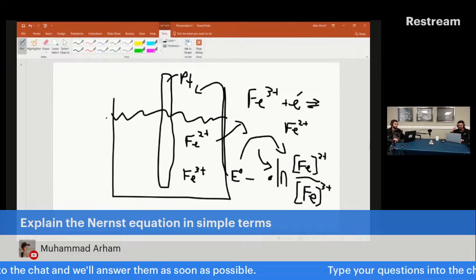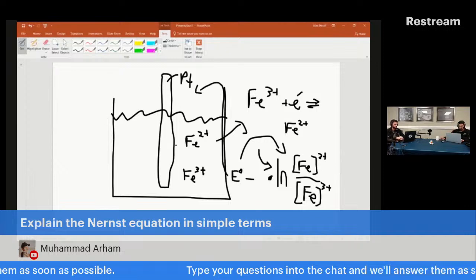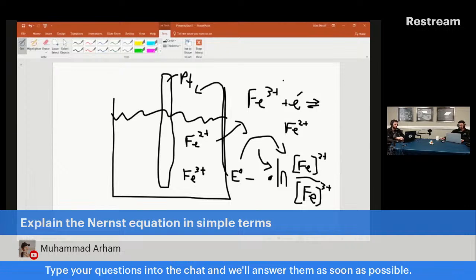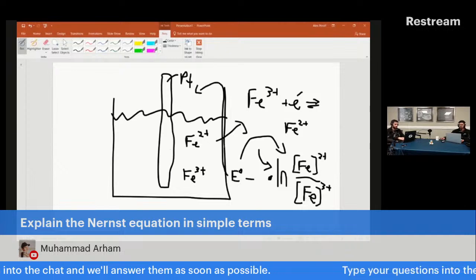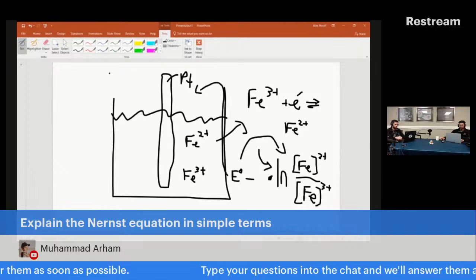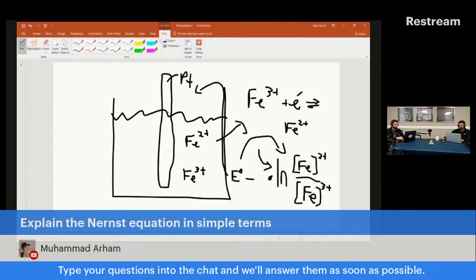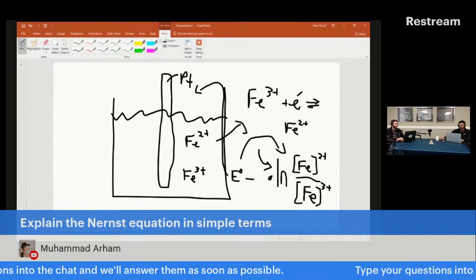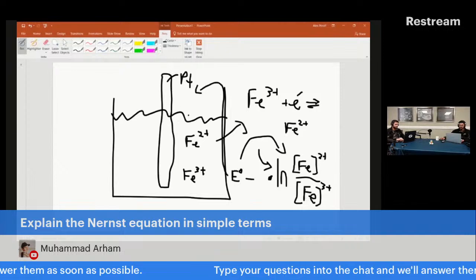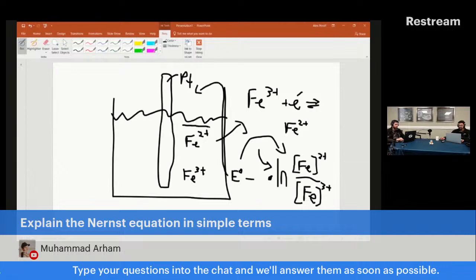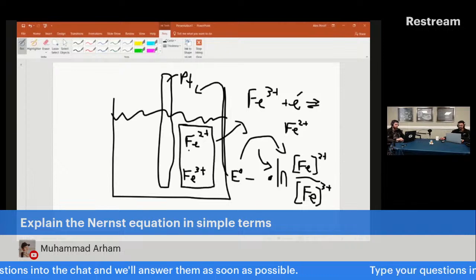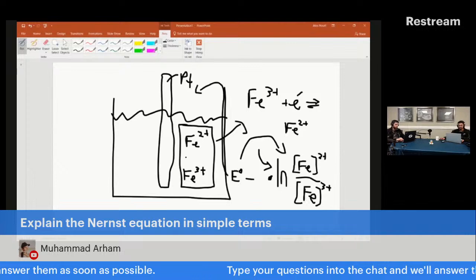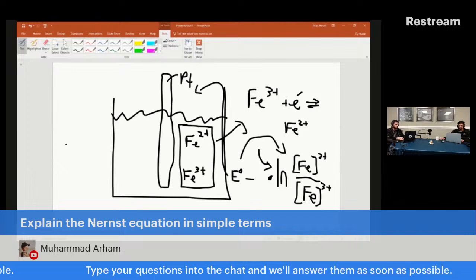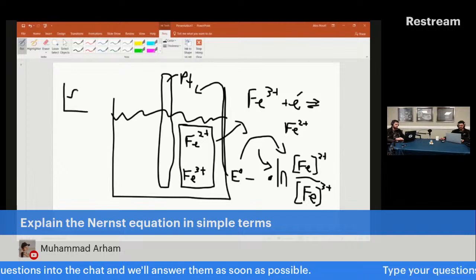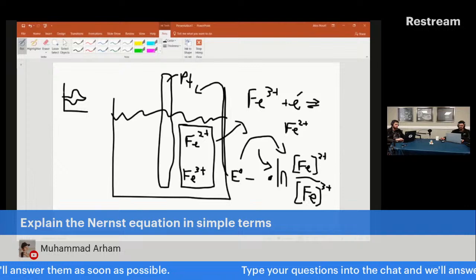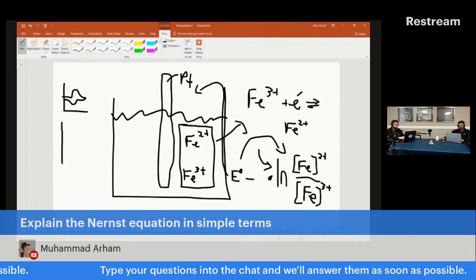And what electroanalytical chemists commonly do is they do things like cyclic voltammetry experiments, where instead of adding both of these species into solution, they'll only put one of them in, and then they'll use a potentiostat, an outside power source, to control the voltage or the potential of that electrode, platinum or glassy carbon or whatever. And they will then adjust the concentration profiles of these two species at the electrode surface. So that is what happens when you do cyclic voltammetry and you get this little duck and stuff like that. There's also a concentration profile change over time.